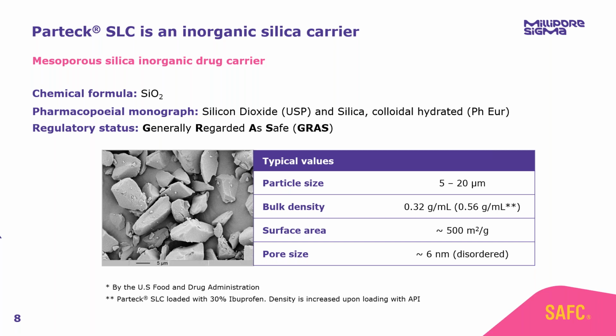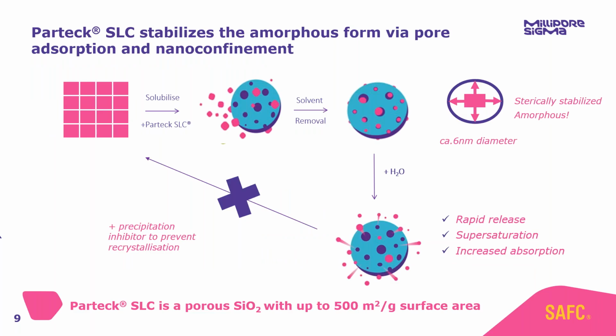The other important property for mesoporous silica is the pore size. Mesoporous, by definition, is anywhere between 2 and 50 nanometers in diameter, so a relatively large range. But for this mesoporous silica, Parteck SLC, the pore size is approximately 6 nanometers in diameter. So it's from these two very important properties, surface area and pore size, that the functionality of this excipient arises. Specifically, mesoporous silica stabilizes the amorphous form via adsorption to the porous network, so taking advantage of that high surface area. And then secondly, via nano confinement, so taking advantage of that 6 nanometer pore size.